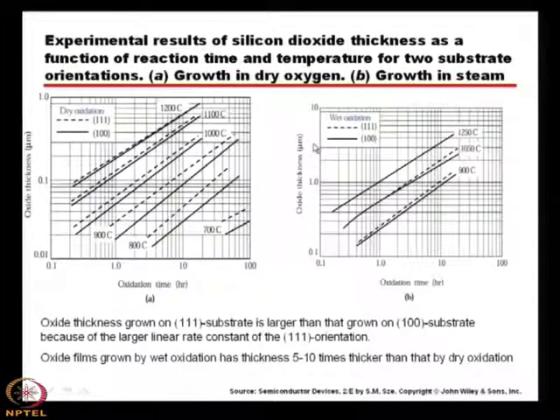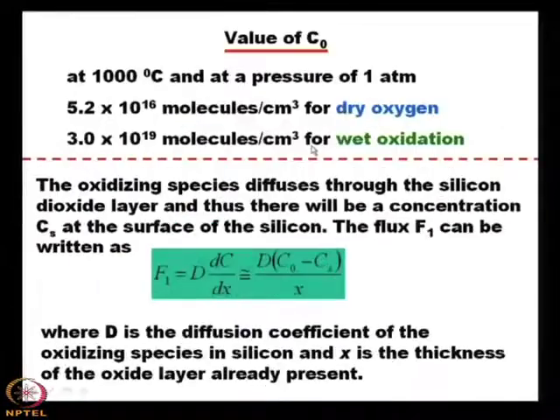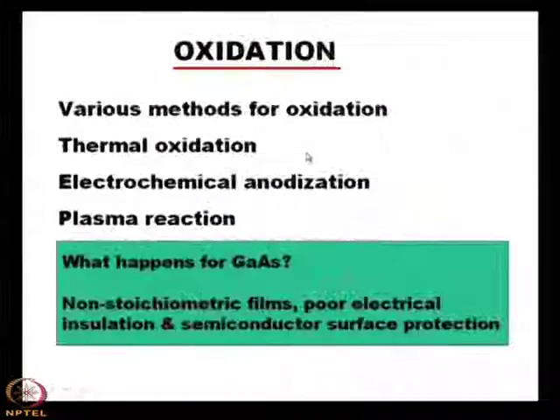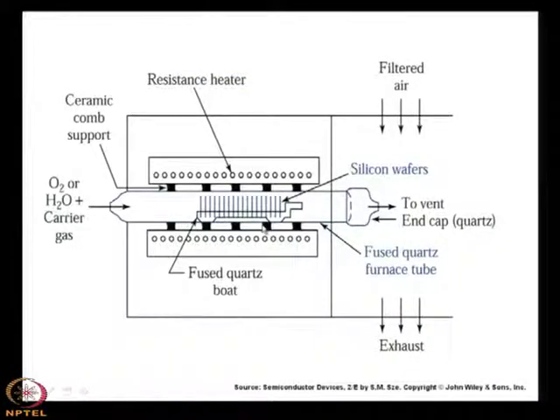So, now we see that the vertical furnace is the most efficient furnace compared to the horizontal one, working at normal atmospheric pressure, that is 760 millimeter of mercury, and at low temperature, meaning 800-900 degree centigrade, so that it becomes a slow process and the thermal shock is not there. At one go, a large number of silicon wafers can be oxidized. So, these are the advantages, and the vertical furnace has its own efficiency.